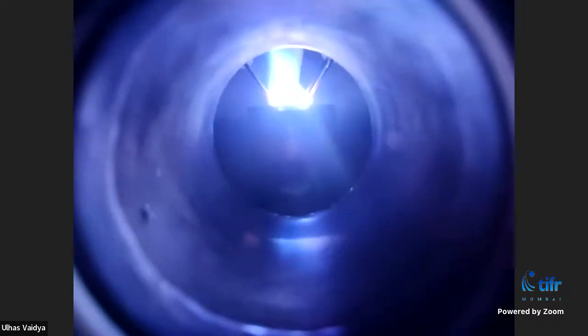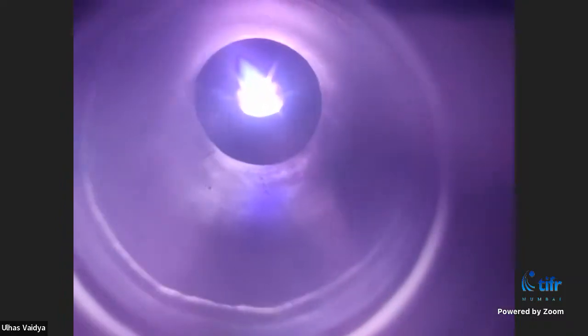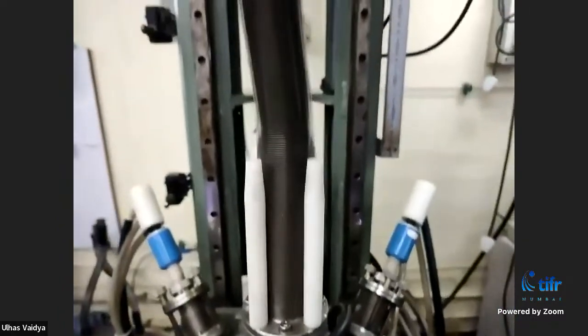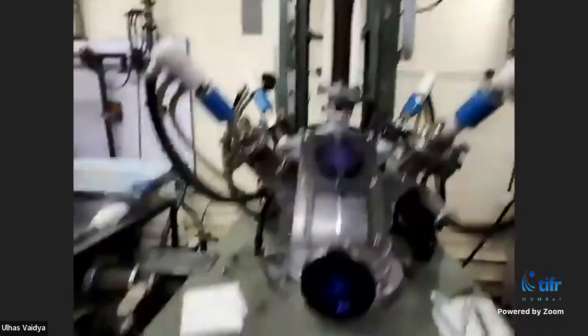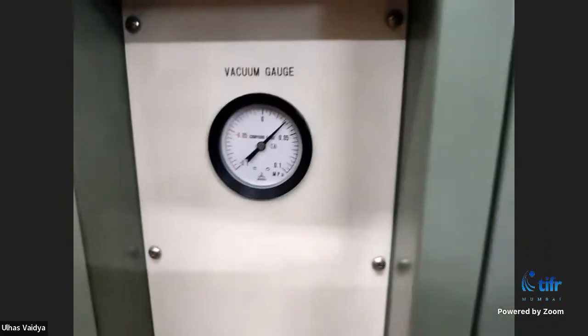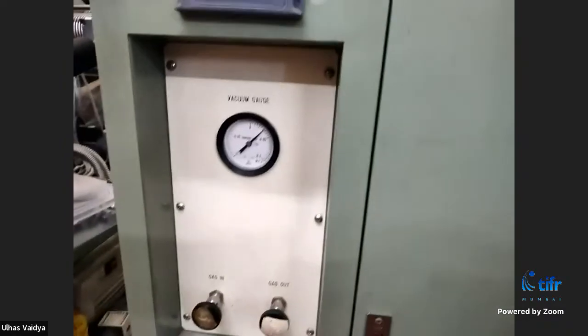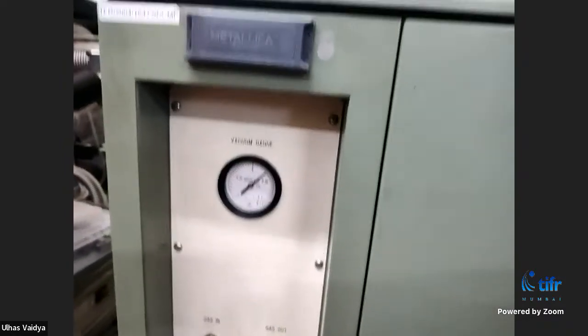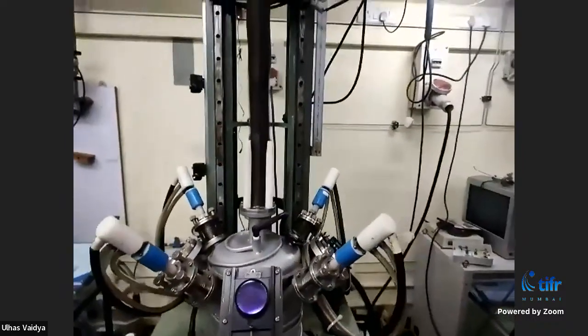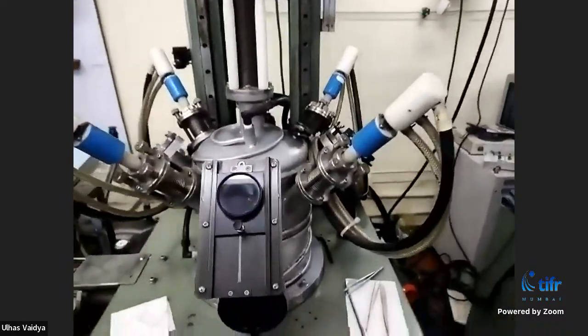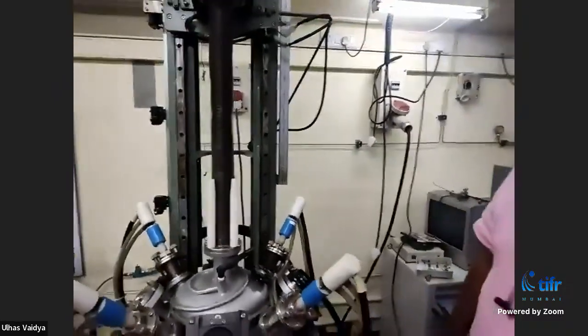All right. So right now, this has become a completely molten solution, but we have to melt it some 2-3 times more before we start the crystal growth of this sample. So you can see that the bellow is bending like this. That is because it has gone above the atmospheric pressure, because of this huge amount of heat inside. It's quite high. So now once I switch off the heating, the bellow has become a normal shape because again the pressure inside has become close to atmospheric pressure.